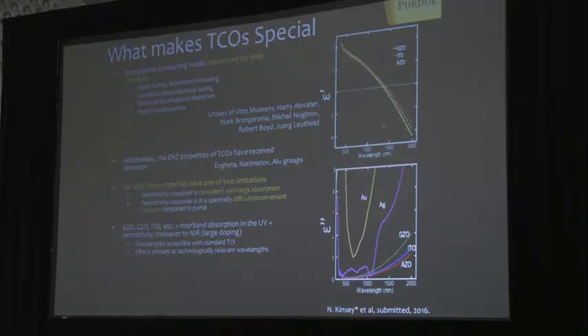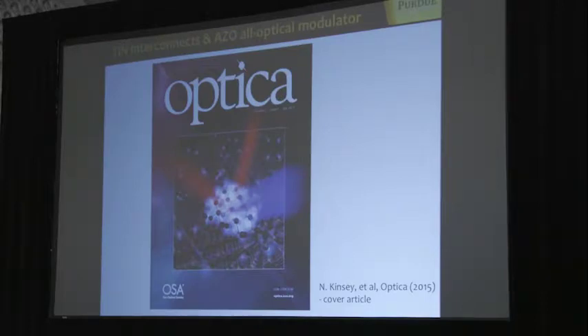It happens around telecom wavelengths, and you could control it, in the case of, for example, aluminum-doped zinc oxide, which we like to work with, by simply changing the aluminum doping. But you see it's around telecom. And if you look at the imaginary part, it's much less than gold or silver. So they actually have smaller losses compared to gold and silver, and AZO, aluminum-doped zinc oxide, has the smallest epsilon double prime. So why is it important?